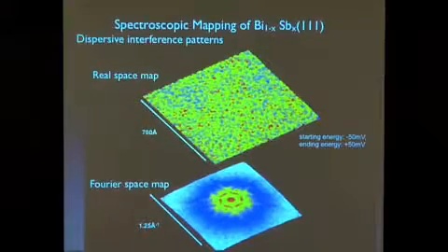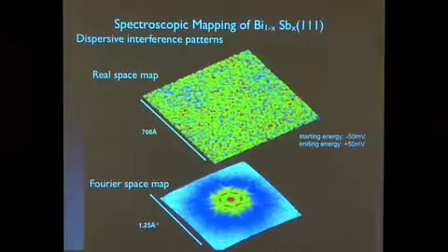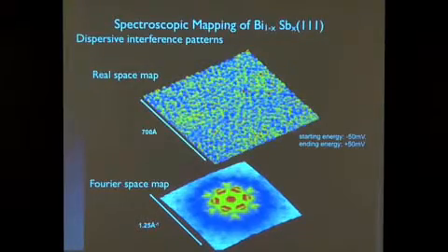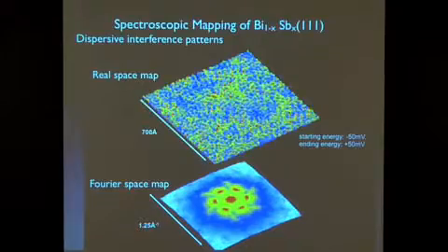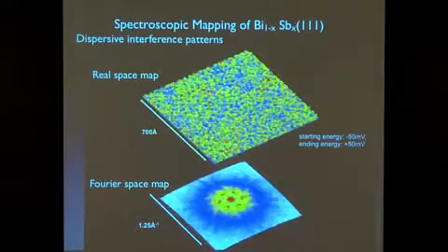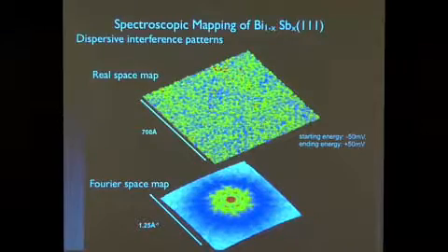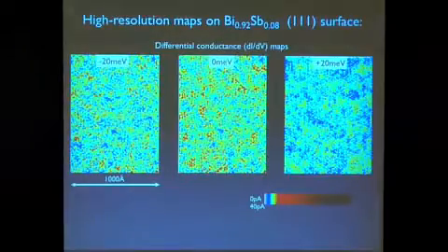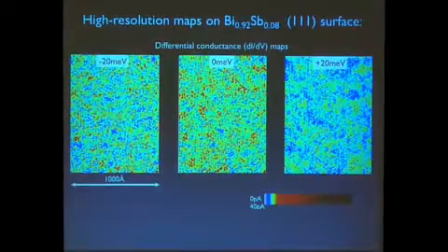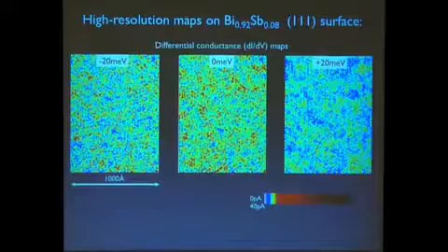So remember, we take the STM. The way we look at these samples is these easily break, and you can expose them to basically an STM operating at low temperatures. And you can go to every pixel, every location on the sample, and measure the rate of electrons tunneling into the sample, and use that to basically build a movie of what the electronic states look like in space as a function of energy, and basically take a Fourier transform of that to look at what are the possible wavelengths that are involved in making the picture that you're looking at. Now, if you do that very carefully, you notice that this is the real space data, which is kind of hard to discern.